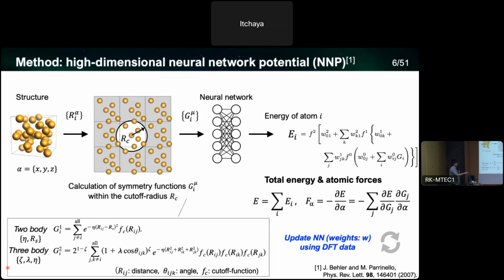Then the parameters, as I mentioned, in the solid lines in the neural network, are updated to well reproduce the density functional theory calculation data. We have a large number of different atomic configurations, and we know the energies of these atomic structures. So we update the parameters to fit these values with the DFT data. This is what we call the training process.